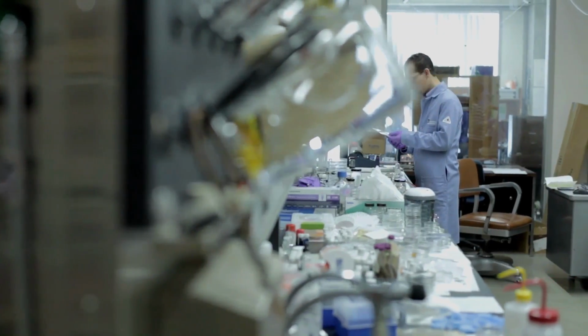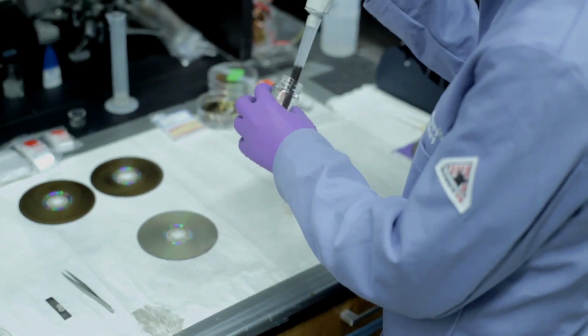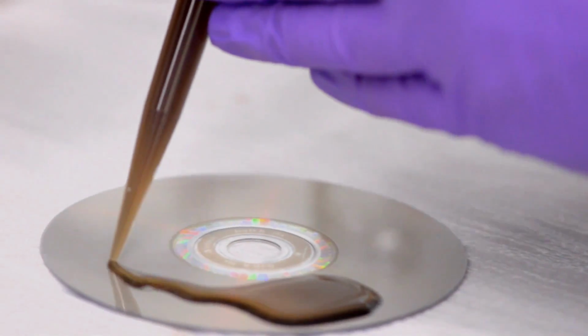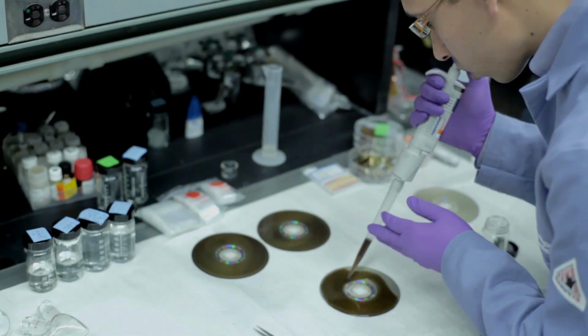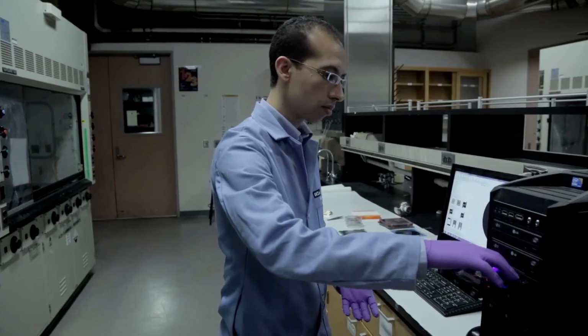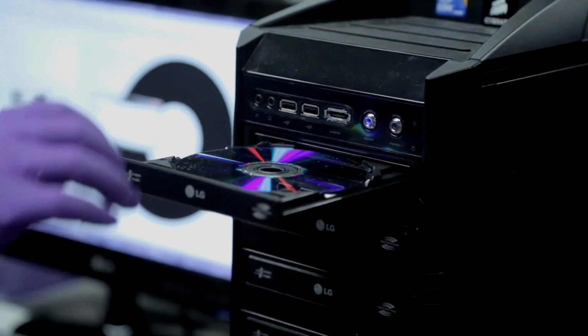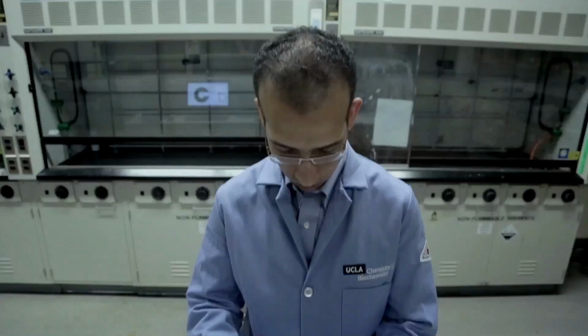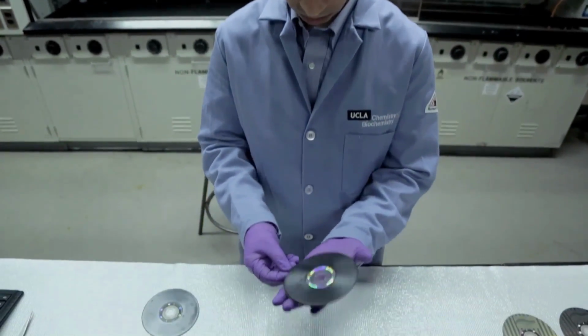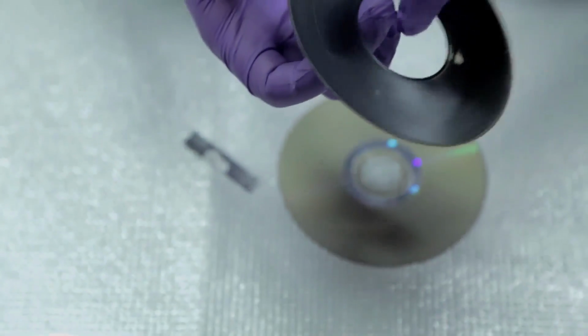We start with graphite oxide, which is a water-dispersible material. We then coat it onto sheets of plastic. We hit it with a light from a laser. Deoxygenates, it turns it into graphene. So it felt very exciting because we made all organic graphene in a very simple process using a consumer-grade DVD drive that you can find everywhere. But the real discovery was yet to come.